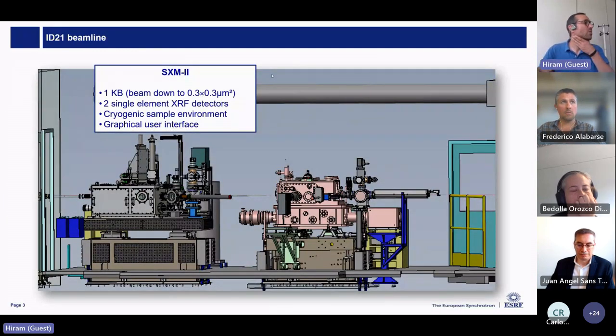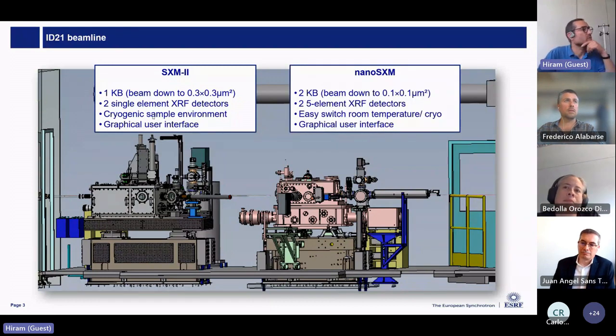So a beamline, as of now, is operating one microscope, one scanning X-ray microscope operating in vacuum with a resolution down to around 300 nanometers. We have single element X-ray fluorescence detectors, and one particularity is that we offer a cryogenic sample environment, which is compatible with biological applications. So we have a way to transfer the sample frozen into the vacuum chamber.